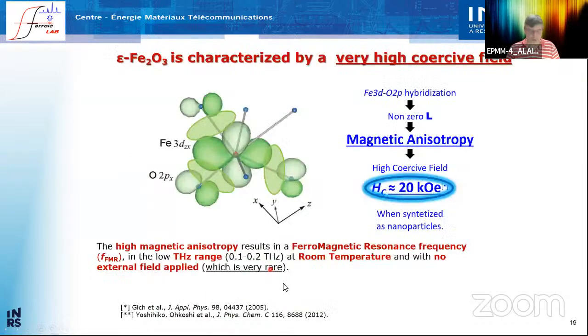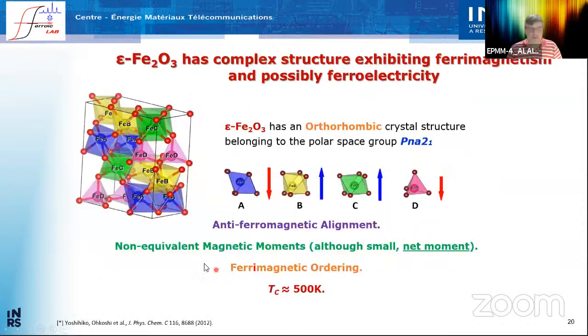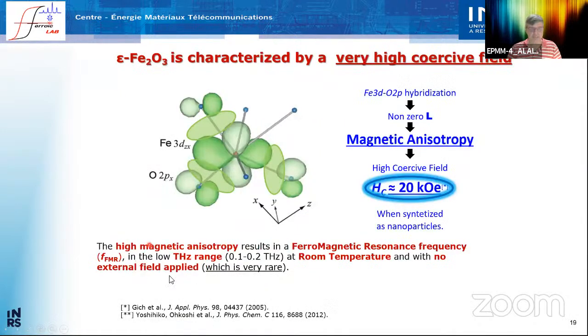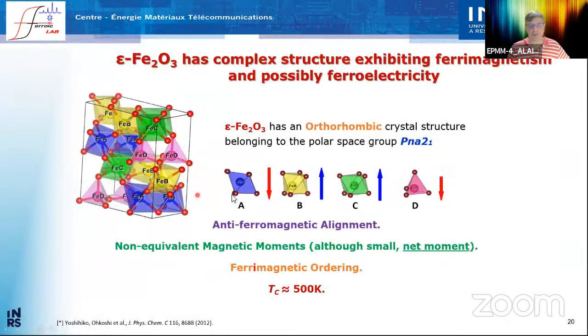Very recently, this material was also interesting because it has the highest magnetic anisotropy of the oxides, and a huge coercive field of 20 kilo-oersted, which has the consequence that it has a ferromagnetic resonance frequency in the low terahertz range, which is also something interesting for application.